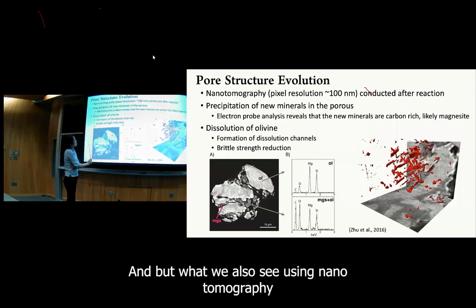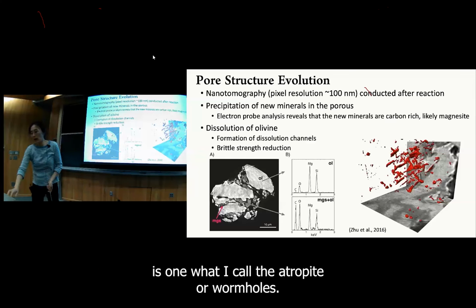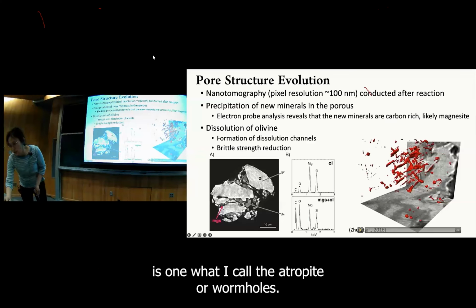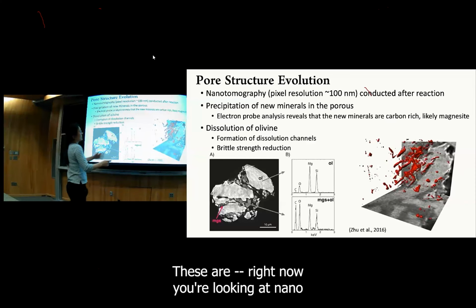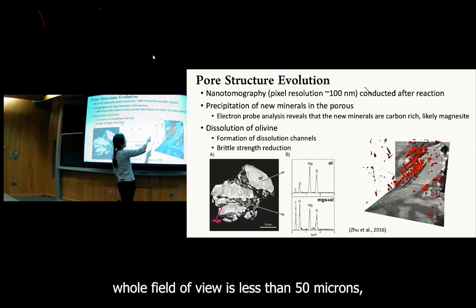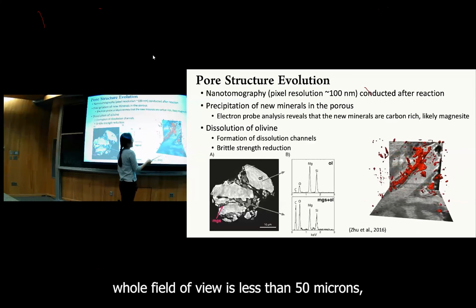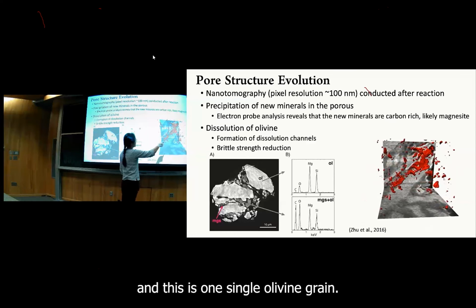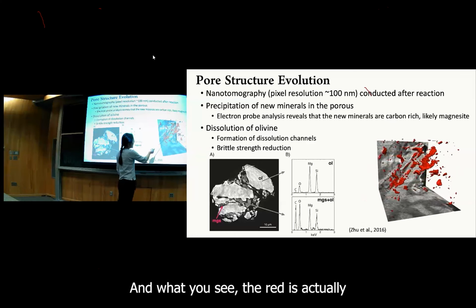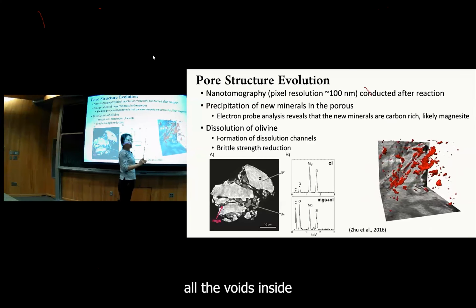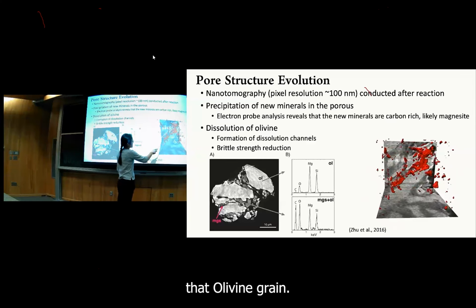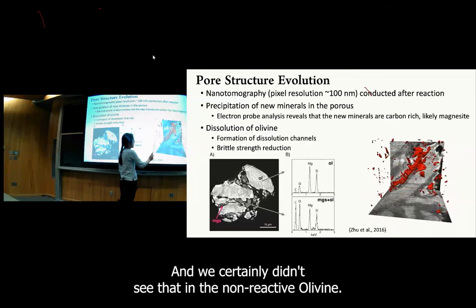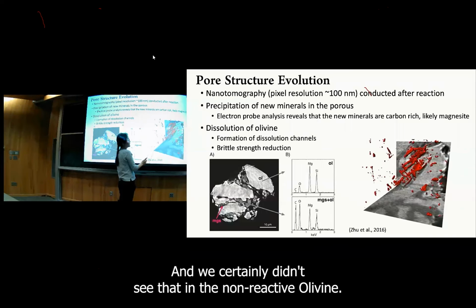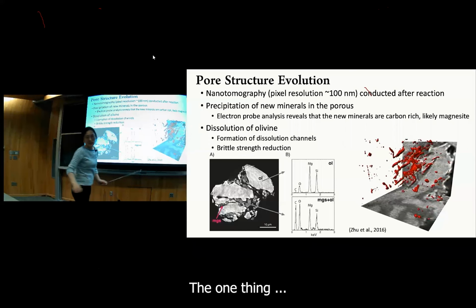But what we also see using nanotomography is what I call the etch pits or wormholes. Right now, you're looking at a nanotomography, and this whole field of view is less than 50 microns. And this is one single olivine grain. And the red is actually all the voids inside that olivine grain. And we certainly didn't see that in non-reacted olivine. This is a good angle, I will stop here.